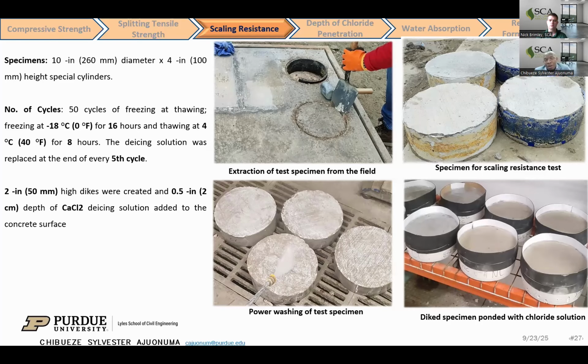So for the test specimens that we used, we had 10-inch by 4-inch diameter cylinders, which were extracted from the field after 28 days of casting. For some of the specimens that had curing compound on them, they were power washed to make the surface clean, and they were kept at ambient condition of 23 degrees until testing. After that, we built a 2-inch dike around them, and then we added the deicing compound, which is calcium chloride, at about 0.5 inch depth.